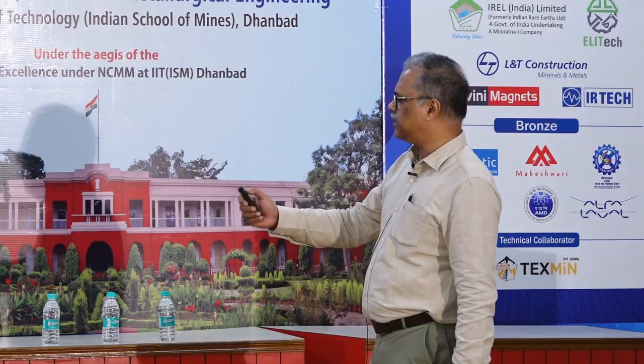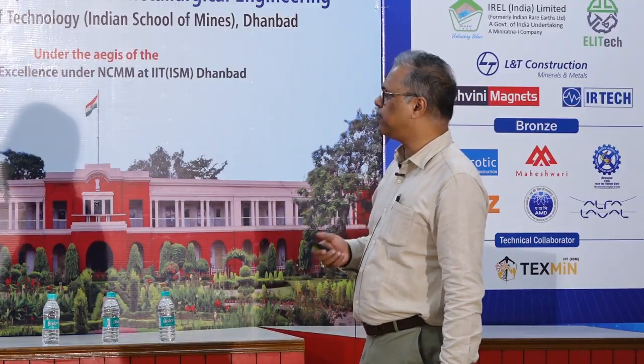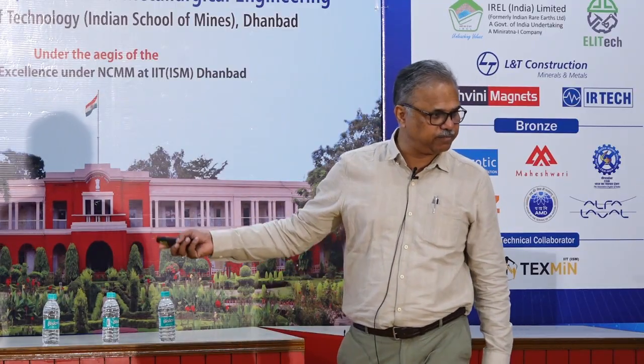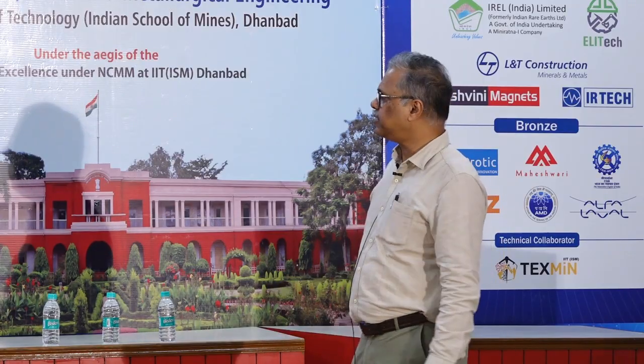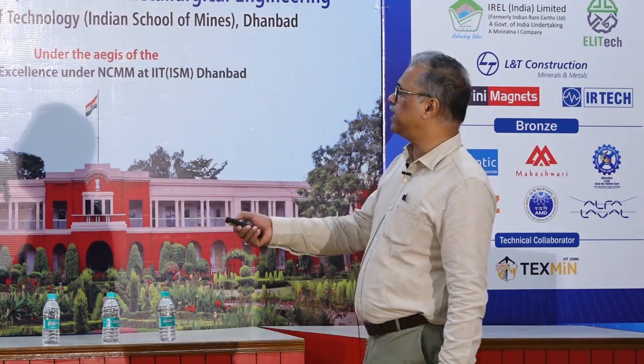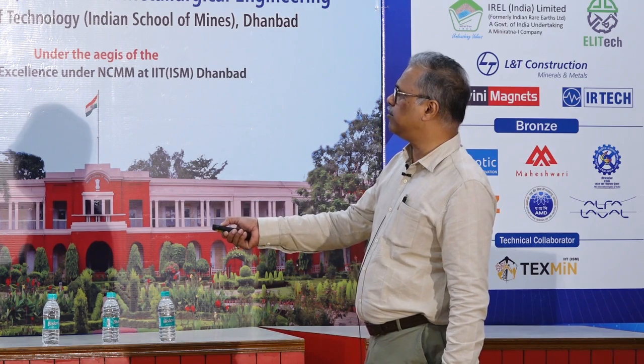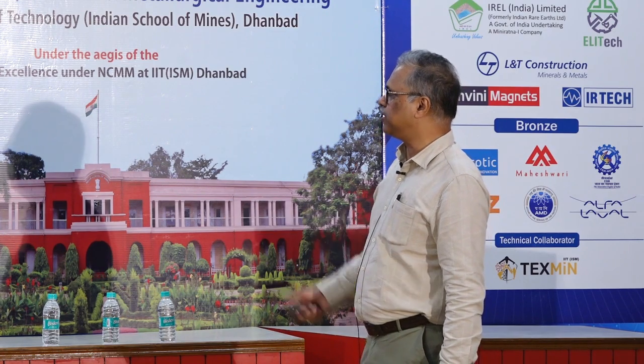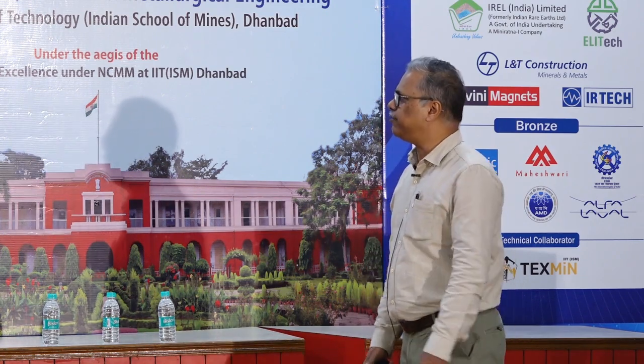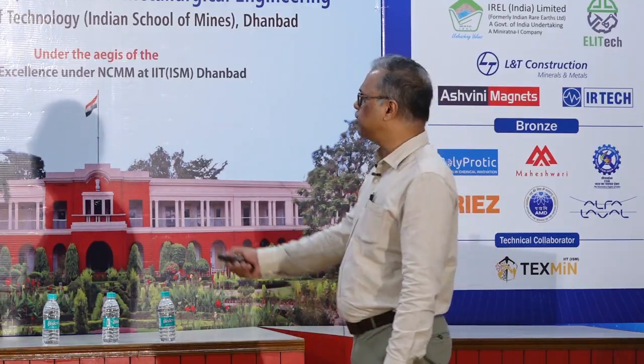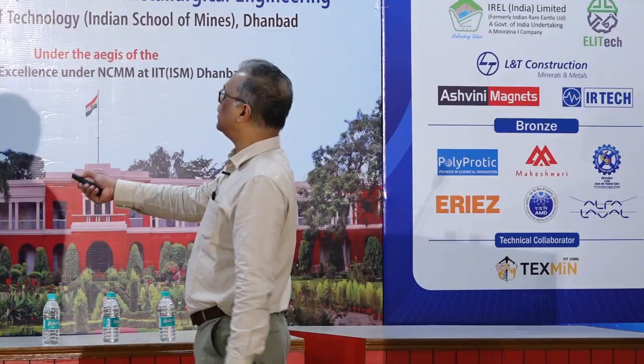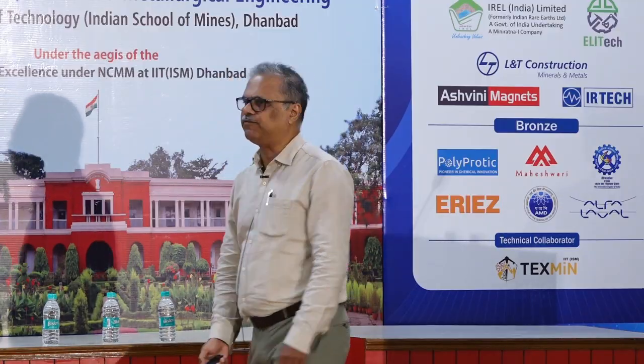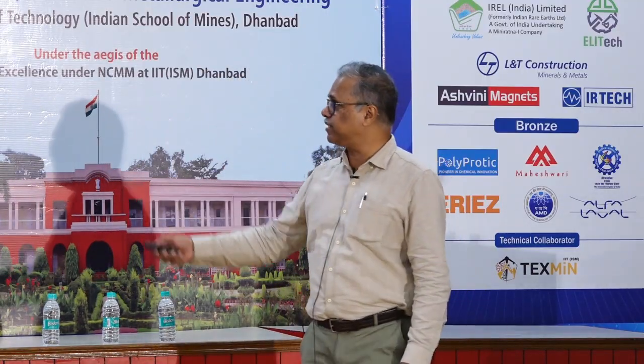What you can see here is a sintered magnet and a hot deformation magnet. I think with that, we can go to the previous one. The red and blue are the magnetization and demagnetization curve. But in the case of the hot deformed magnet, you can find there is a deflection. When there is a deflection in this process, we know that some other process is taking place. So this magnet has two different magnetic phases.